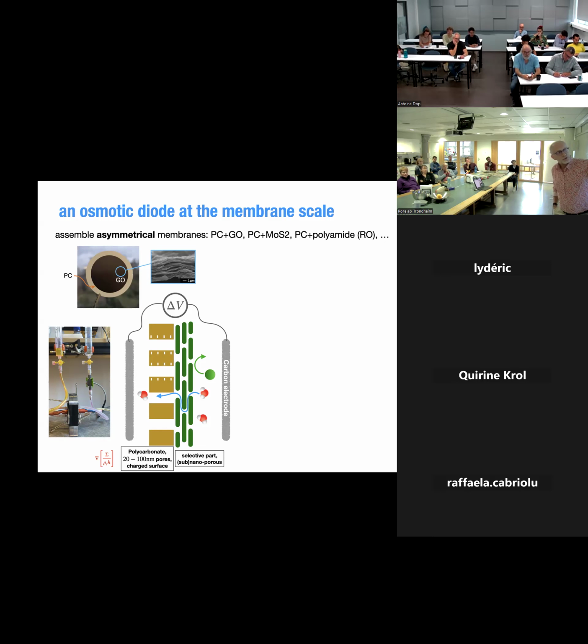And then on top of that, you deposit graphene oxide. Graphene oxide is like a millefeuille, like the pastry, and the thickness between the layers here is in the range of a nanometer. So it's a very good filter that you can cook in your kitchen. That's very easy to do.